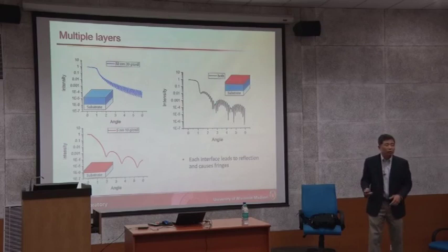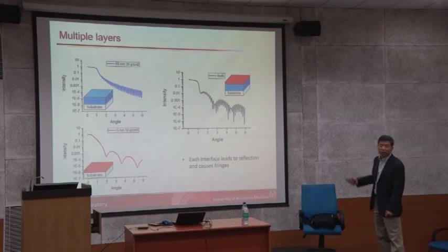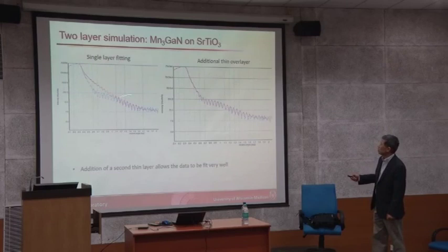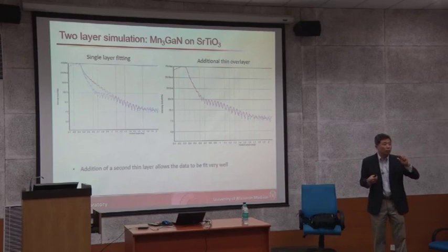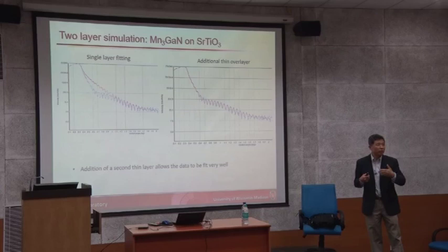With a single layer fitting and double layer fitting, you can fit the data and get information about how much interdiffusion or interface layer you have — without going to TEM or anything else. First check it and determine how good your film is, how thick. Our film — first time we didn't know what it was. We found on top of the surface there was a junk layer. We didn't know what the junk layer was in the beginning. The X-ray fitting was always very strange. Later we found this was coming from oxidation when exposed to air — this layer is like a few nanometers of oxide.